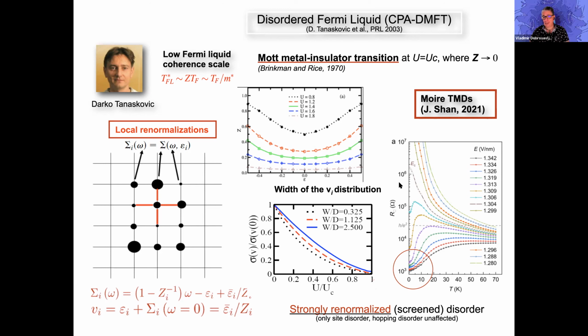And then I find that this local effect, the Mott-Hubbard effect, which is unrelated to the long-range Coulomb interactions, is the repulsion between two electrons in the same orbital. That effect tends to strongly suppress disorder. And why is that so? Because when you put in disorder, you can understand it in this way. The local occupation should vary quite a bit, as we've seen in Maria's calculation. Now, if you approach the Mott insulator, it should have the same occupation on each site. So you can understand that as you approach the Mott insulator, the density fluctuations should be suppressed. And in fact, that means that the renormalized disorder should also be suppressed.